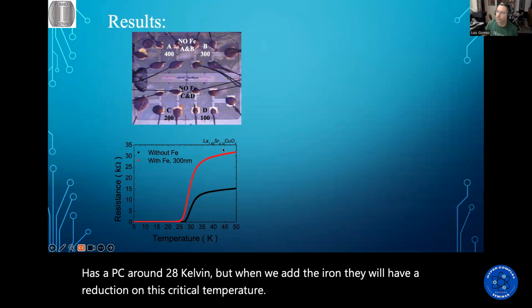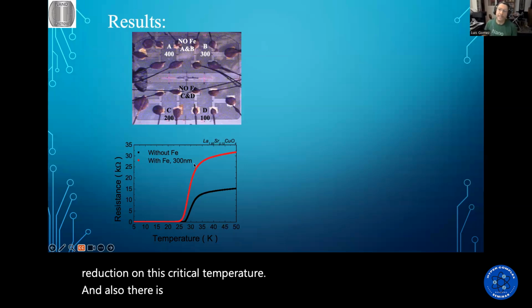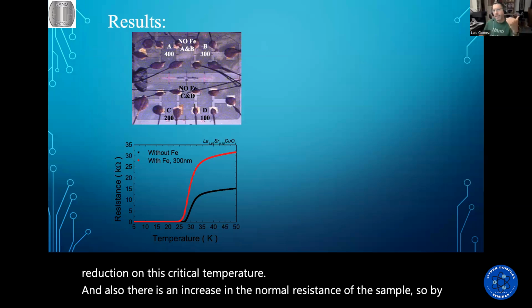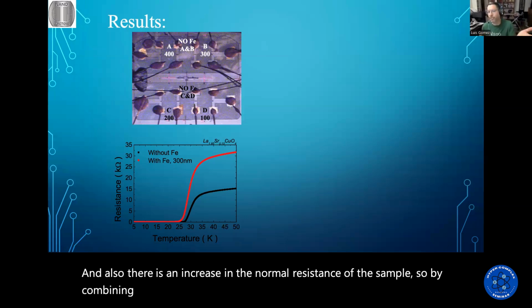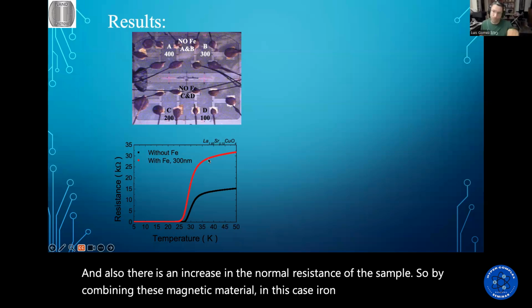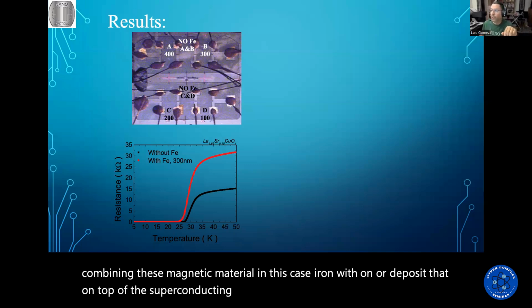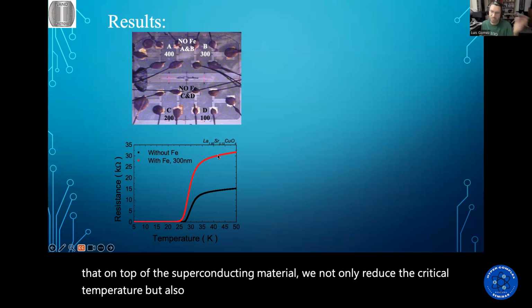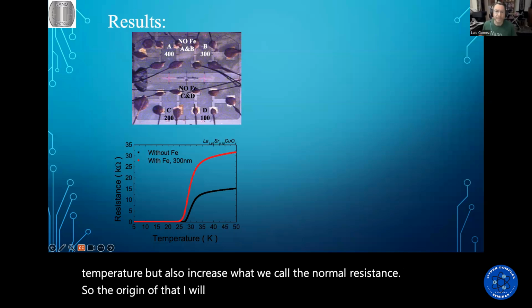And also there is an increase in the normal resistance of the sample. So by combining this magnetic material, in this case iron, and depositing that on top of the superconducting material, we not only reduce the critical temperature, but also increase what we call the normal resistance. So the origin of that, I will explain later.